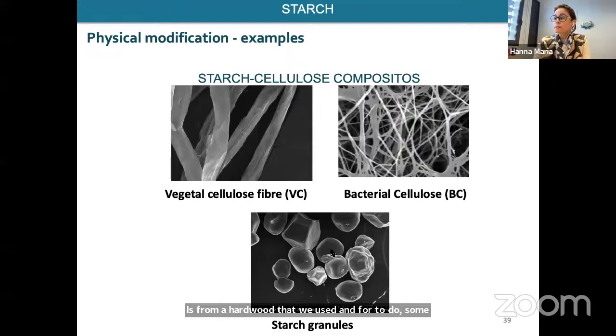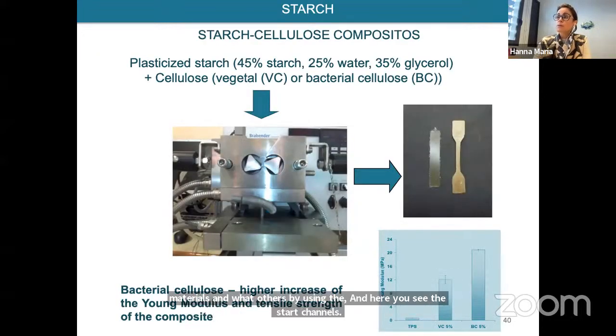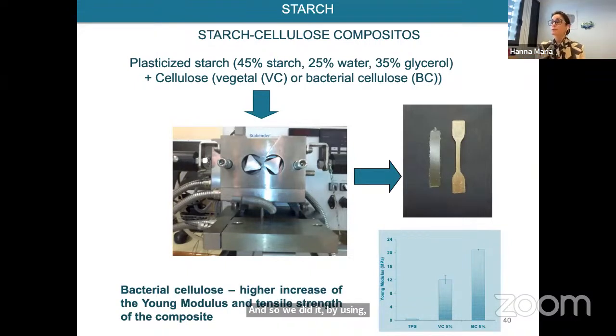And here you see the starch granules. We made it using 45% starch, 25% water, and some glycerol to give some flexibility. And for the cellulose, we changed the quantity. Here I have an example using 5% cellulose. And we did it using this melting equipment. And you can see here, we then had some composites using bacterial cellulose and vegetable cellulose.